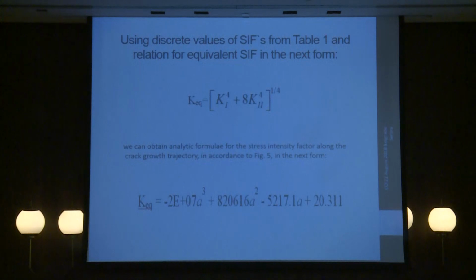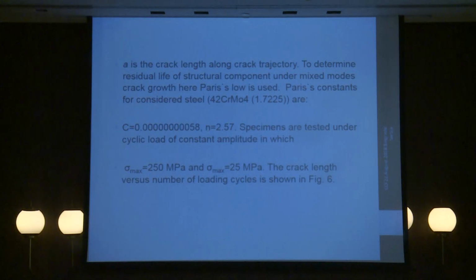And then this is the expression for calculating the equivalent stress intensity factor, and how to obtain the analytical formula for the stress intensity factor along the crack growth trajectory. This is a formula we can use for every new case, because in the literature we have no expression for this. So using these methods we can obtain this formula for the future. The Paris constants we get from the experiment for this considered high quality steel. The load introduced in the specimen had a maximum stress of 250 megapascals and a minimum of 25 megapascals.